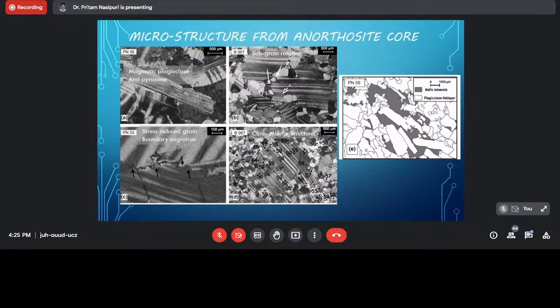And I have measured the anorthite content, which again shows that there is no great change in the anorthite content of the material. There is no big change in the anorthite content. We can safely conclude that the deformation mechanism is mostly due to the difference in the mechanical energies or mechanical properties of the rock, and it is not driven by chemical potential.